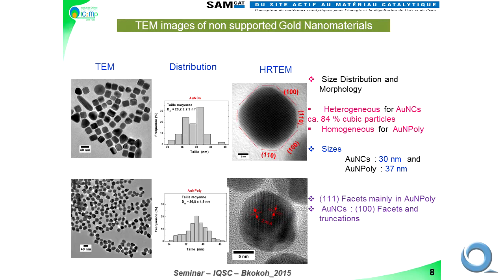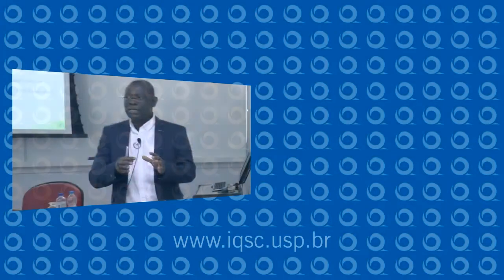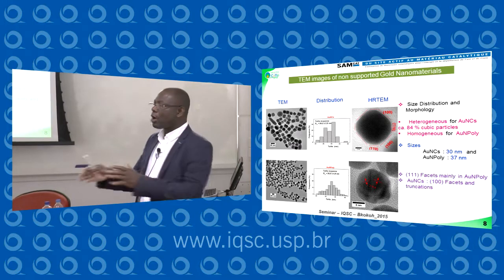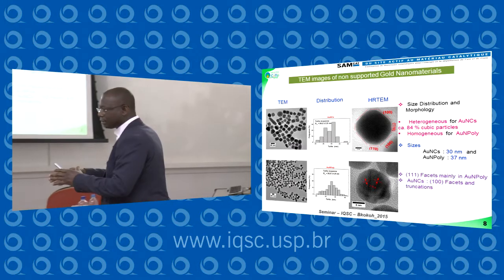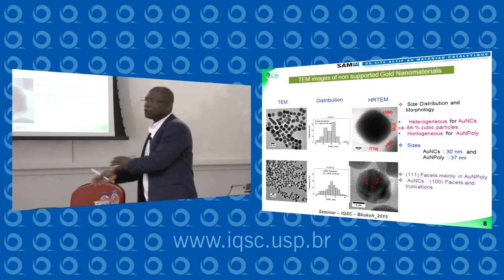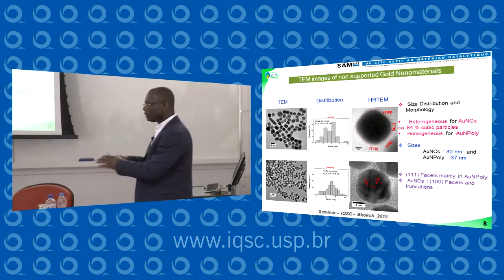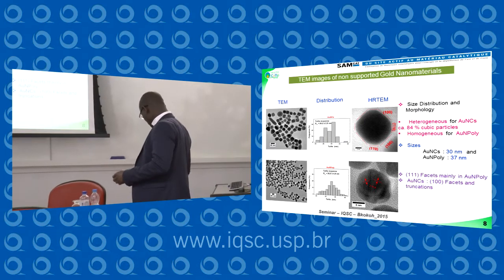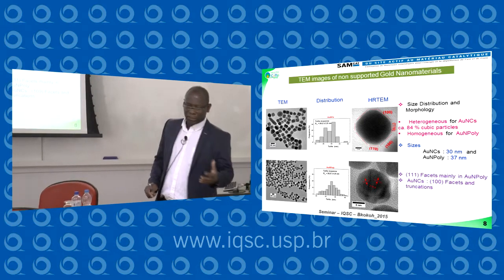And if you have polycrystalline, for example, polyhedron catalyst, mainly you have 111 facets, and icosahedron and so on. This means that by the convolution, we can estimate the number of 111 facets, 100 facets, and 110 facets, for example, in the polycrystalline. We have some methods in our lab.